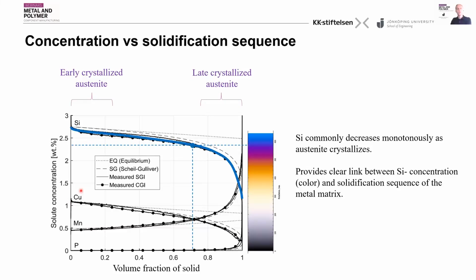Another thing you can note in these profiles is that silicon continuously decreases as the volume fraction solid increases. So the more silicon decreases, the more the material solidifies. And this means that, since after the color etching the silicon concentration is reflected by a color, a certain color will correspond to a certain moment in solidification when this austenite crystallized. And this makes it possible to use the color etching to understand what parts of the metal matrix have solidified before other parts by looking at this color scale and comparing.